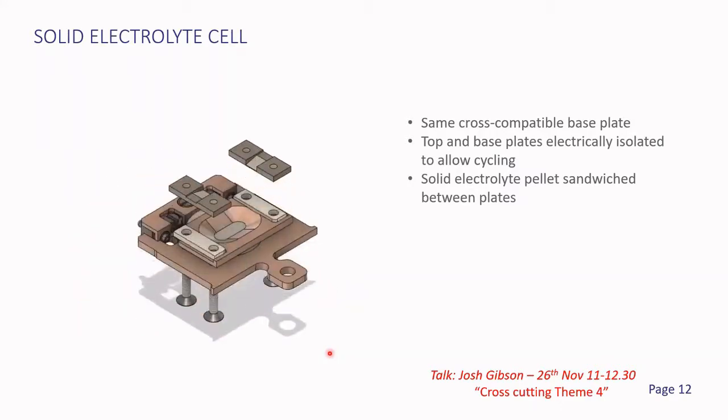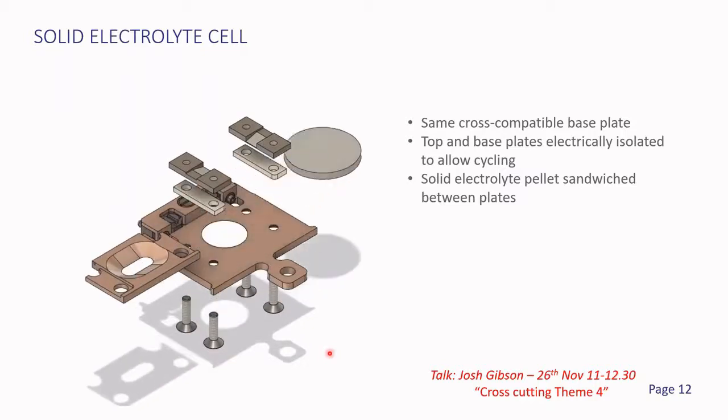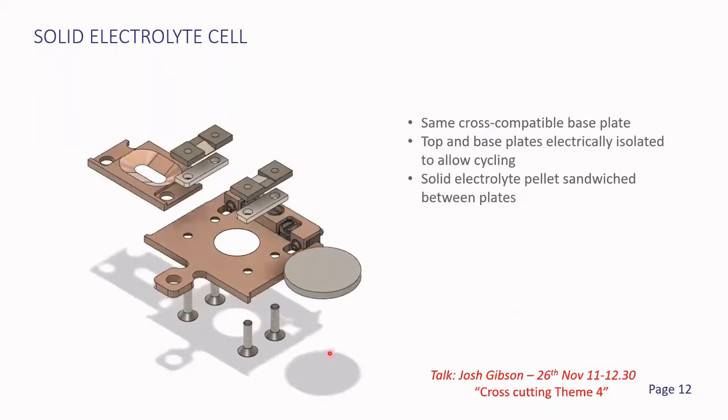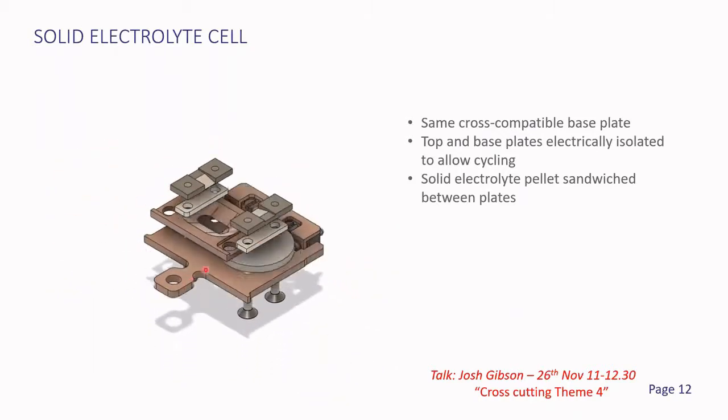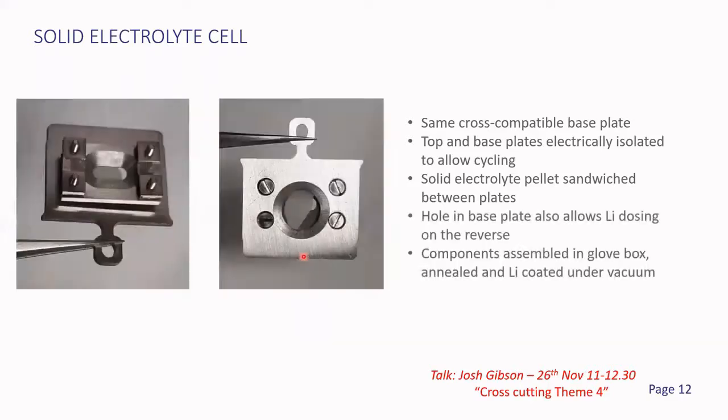These plates are compatible with many instrumental facilities, such as the HAXPES, the Royce Institute in Manchester, and with Diamond I09 Beamline, who are actually designing this electrochemical plate. There are some Macor ceramics that can be seen to provide electrical insulation between the bottom and top electrochemical plates, whilst also being thermally stable up to high temperatures, so that we can anneal the solid electrolyte pellet to clean it. The photographs here show the top and bottom view of a prototype cell, which doesn't yet have the electrochemical connections on it that would sit around the back here.